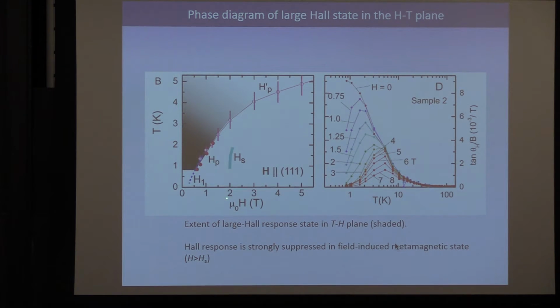So this boundary, somewhere here, you go through a metamagnetic transition. So the field, the applied field, is forcing all the local moments to line up, and then they order. Because in the neutron diffraction, they see this very broad diffuse background condensed into bright Bragg spots, magnetic Bragg spots. So over here, it's probably ordered magnetically. And my comment was that you get magnons here, probably, right? Because you saw that the kappa XX made an abrupt jump, right?